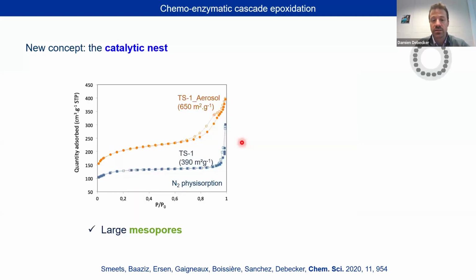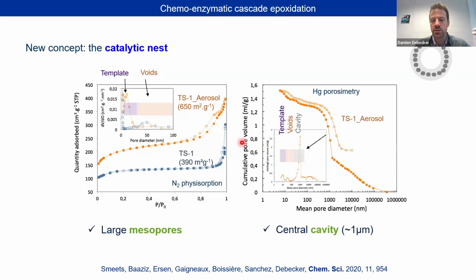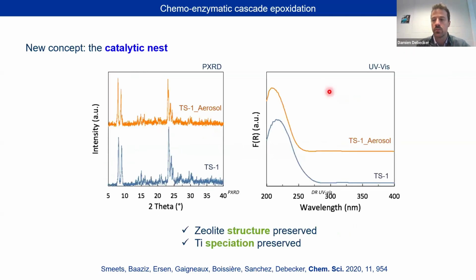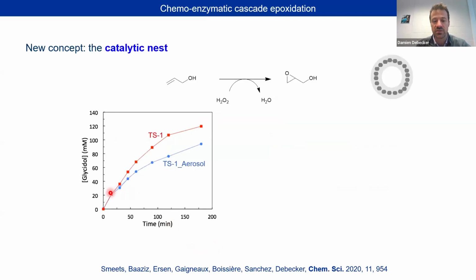We have, of course, characterized all these particles. I will go very quickly here because there's no point in going into the details, but basically we check that we have the microporosity, the mesoporosity between the crystallites, and also the cavity here that is tested by mercury porosimetry. We check also that the zeolite itself is not affected. We still have the same signal in XRD, the same signal in UV-visible spectroscopy. So that means that the speciation of titanium is preserved. And of course, because of that, we have an activity that is preserved.